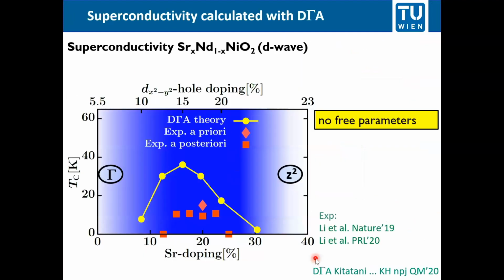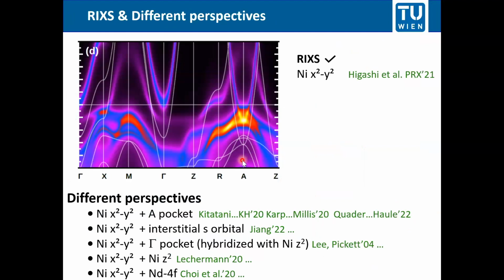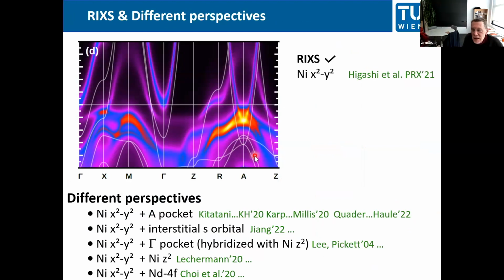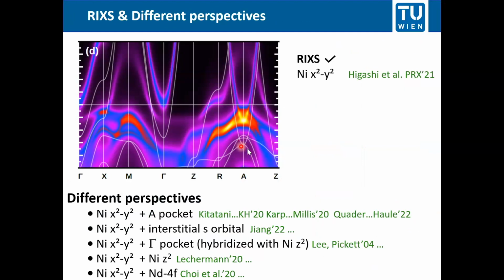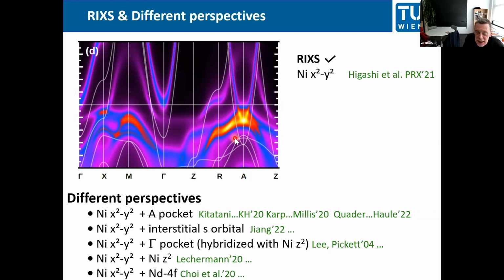Yes, so it's doing a reconstruction. So the A pocket actually goes much further down here if you look at the original A pocket. But then it reconstructs with the other nickel orbitals. So it doesn't hybridize with the nickel x squared minus y squared, but it hybridizes with the nickel xy, for example. And therefore it ends here with the reconstruction instead of going further down. So if you shift it up, it will always end here at the bottom of the other nickel orbitals. So in a way, it is much deeper than it looks like because of the reconstruction. It ends here then, but it is therefore much less susceptible to move up. I see. Thank you.